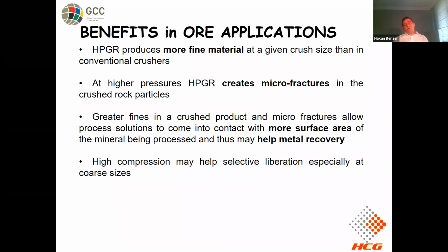Also, we measured microfractures in the HPGR products under the microscope, but also in some cases, especially within the cement industry, we measured this through the work index change of the ball mill feed. It dramatically reduces the Bond work index because of the fractures created in the ore body, if of course the high compression can be implemented onto the material.